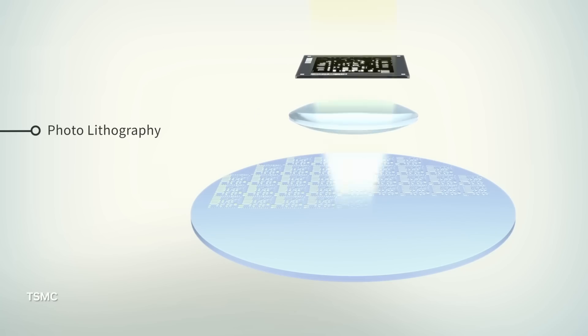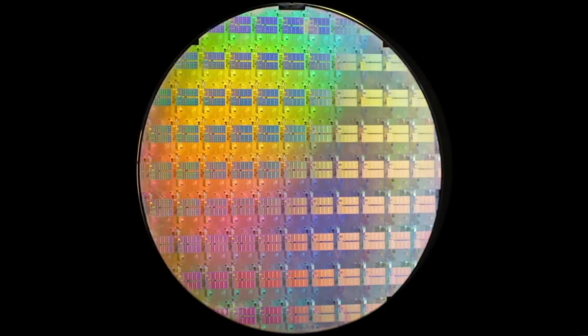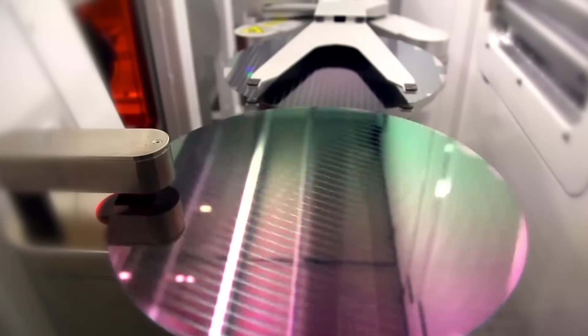However, this was a great challenge and error-prone, because it was hard to achieve precise alignment between patterns in different steps. Any misalignment causes defects and huge yield loss. For their seven nanometer chips, SMIC is reportedly using five to six stages of multi-patterning, meaning they have to expose each wafer five to six times to draw a single transistor feature. This is why it took them quite some time to bring this technology to mass production — they've achieved essentially the same thing as TSMC did, just about six years later.